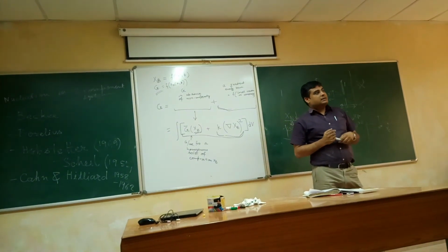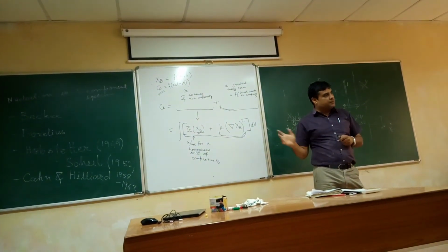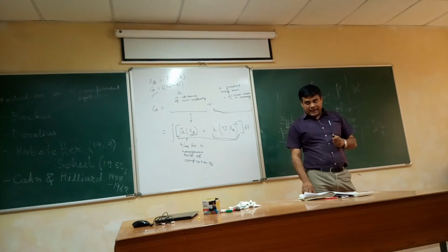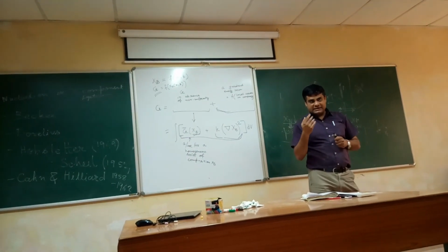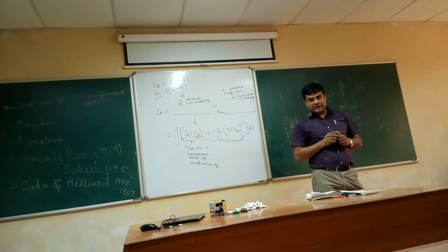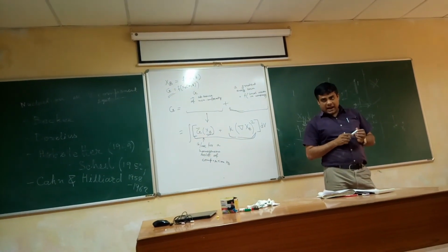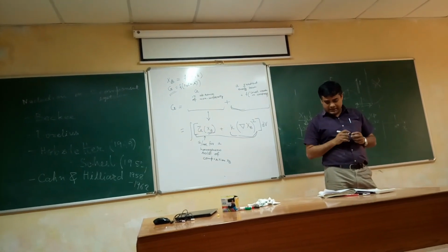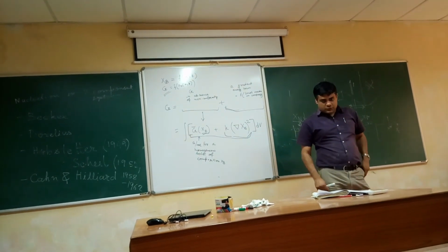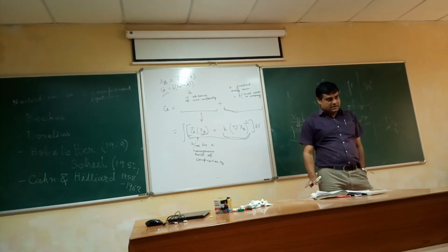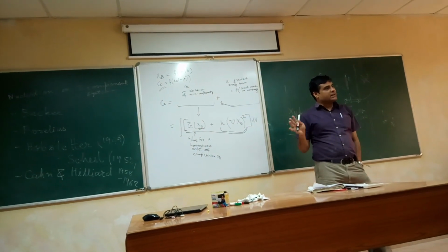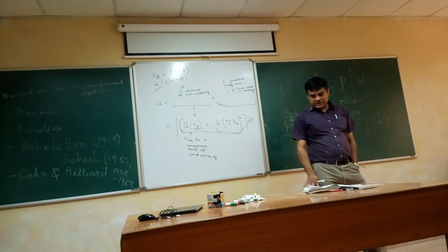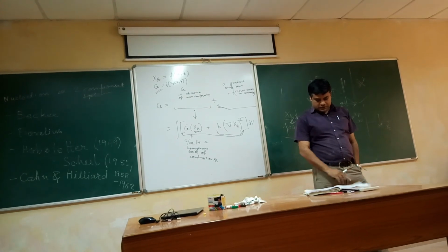So whatever the classical nucleation theory says, they also found out that those are being met, and also that as temperature becomes close to transformation temperature, your R star and your activation delta G star become infinity. So all those situations are met.